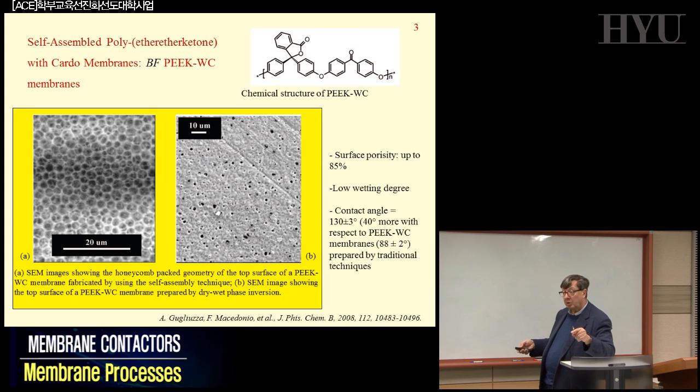But if you put water with alcohol or water with acetone, the droplet size is different. So you can have the same morphology, all equal, but a different size, by changing the composition of this phase inversion in a controlled atmosphere, basically.